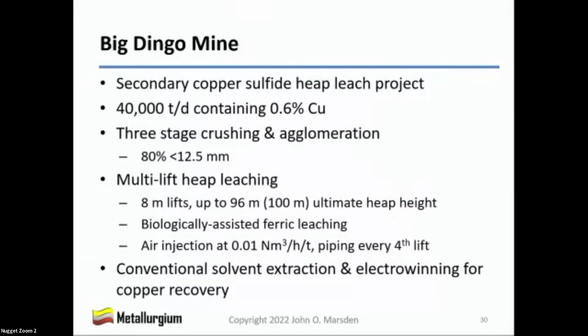Now, like all secondary copper sulfide heap leach projects, it was designed with air injection into the heap. And in this case, the air injection piping was to be installed every 4th lift to provide air for up to 4 cycles of leaching. And the leach pad was designed to an ultimate height of 100 meters with a total capacity of 146 million tons. So a big heap.